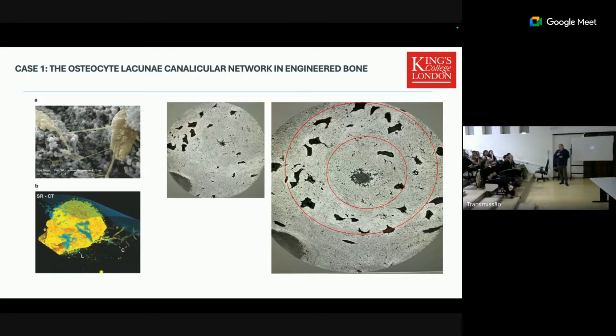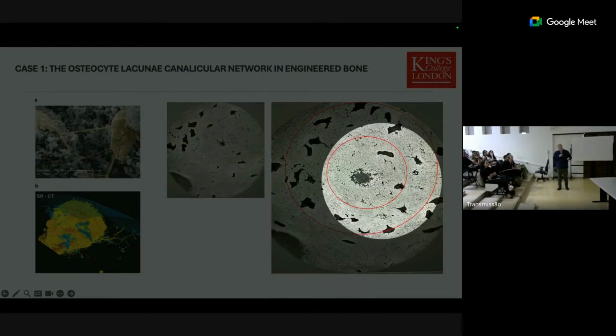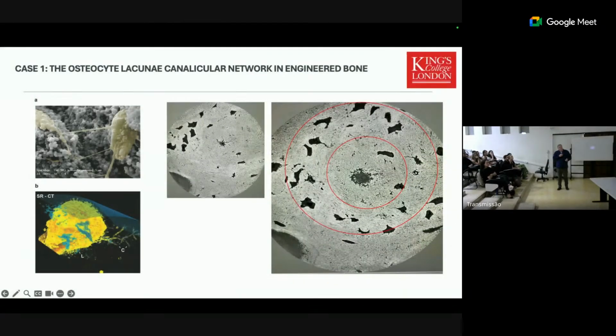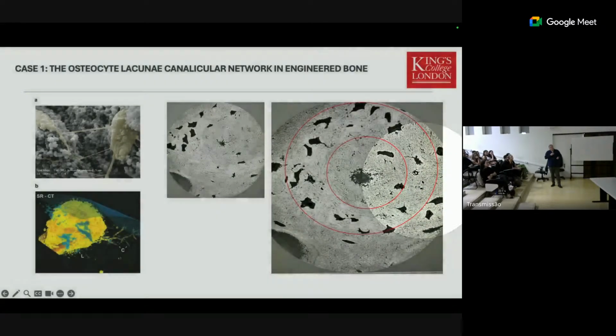And then we come to grafts. And so here's the same type of imaging data on the right-hand side. What we have here is just a projection through that tomograph with the graft material in the middle that hasn't completely healed. And then we can see the osteocytes are starting to form around that grafted material. And hopefully it projects well enough in here that we can see that actually where I've drawn the 2 red circles, in between there, the mineral density is higher.